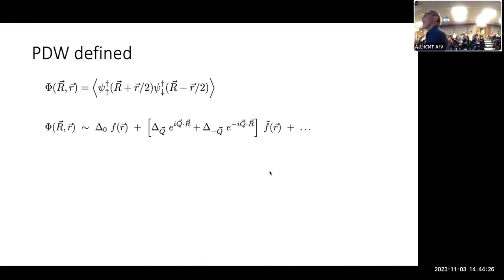Okay. The sorts of pair density waves I'm going to have in mind is the case where we have a pair field that has perhaps a uniform piece, which I'll call delta naught. It might have a D wave form factor. That's not going to be important in this discussion. And then there's going to be a modulated piece at some wave vector Q. These are 2 independent complex order parameters in this case.